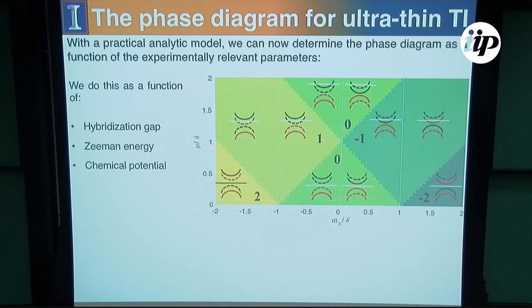What we can see here nicely is that I've tried to plot out the different sector 1 and sector 2 contributions and all of the different crossings, assuming that this white line here is the chemical potential. As we move the chemical potential up, we can go through different Chern numbers, and as we increase the Zeeman splitting, we also get different Chern numbers that change as we close the gap. But crossings that occur up in these bands here, where we move one band across the other band, are not going to change the Chern number because you haven't actually closed the gap anywhere.